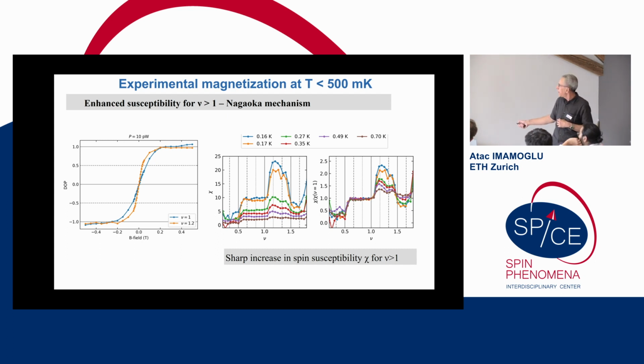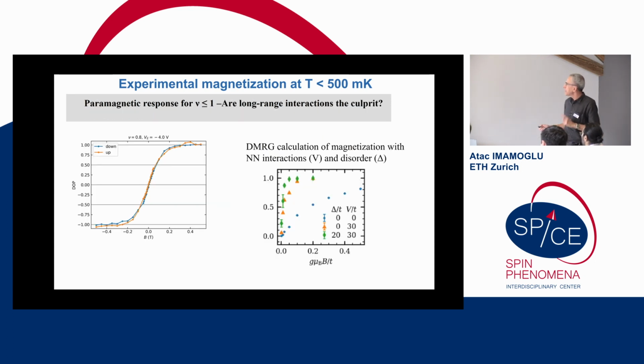And then this dip at 4/3 is very reproducible, and we attribute this to the formation of a generalized Wigner state, which again suppresses the hopping. Okay, so that actually brings us to the question of why do we see one kind of kinetic magnetism and not the other? And this, again, we understood by going back to DMRG, where Ivan introduced disorder as well as nearest neighbor interactions. And this is now the magnetization curve as a function of the magnetic field.